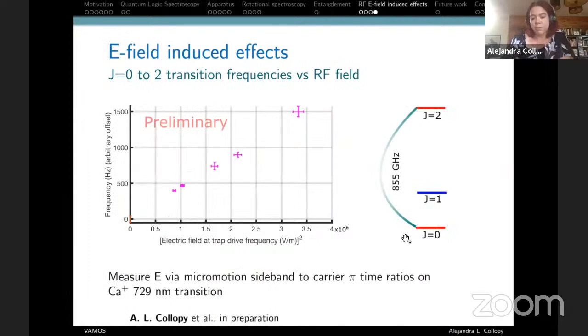So we performed this experiment. We put our ion in different places in our trap so that it sampled different RF electric fields, and measured some J equals 0 to 2 transition frequencies. We started in a state in J equals 2 that's relatively unshifted by this. We're able to measure this RF electric field using sideband-resolved carrier pi times on calcium's quadrupole transition. I've plotted here the electric field squared so that we expect a line.